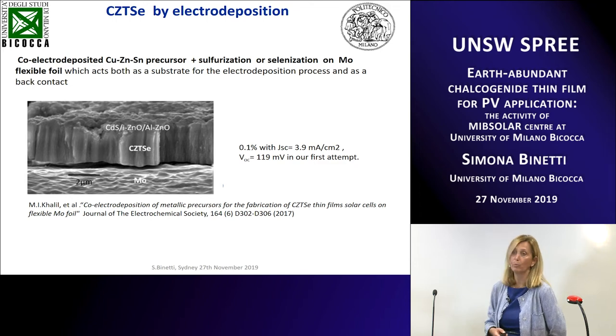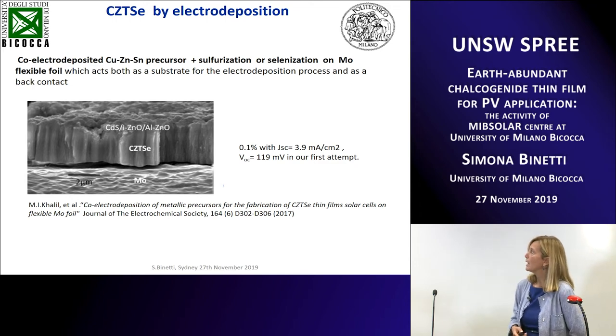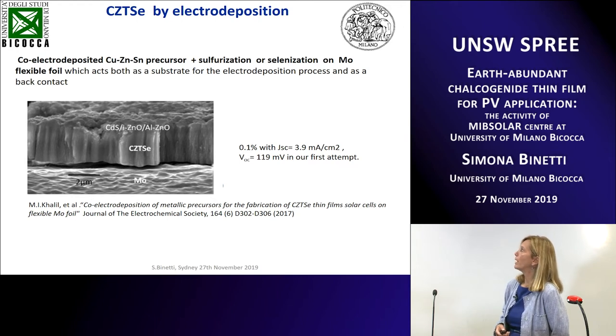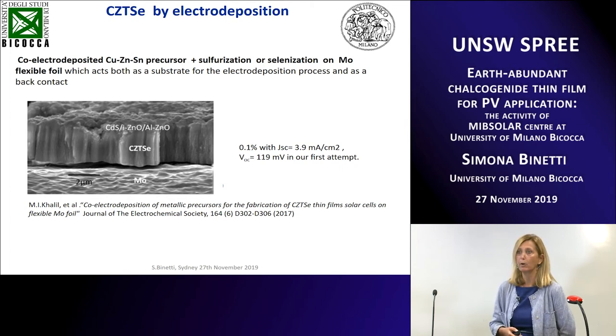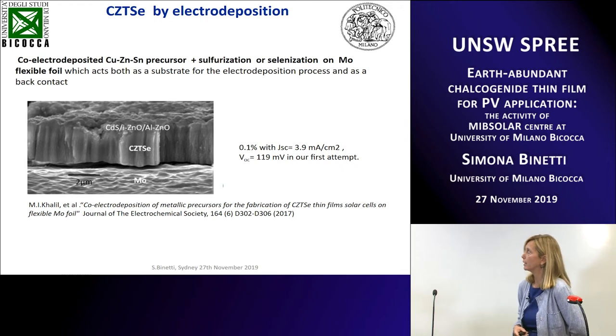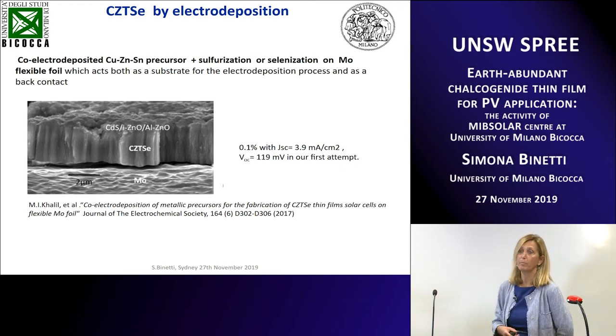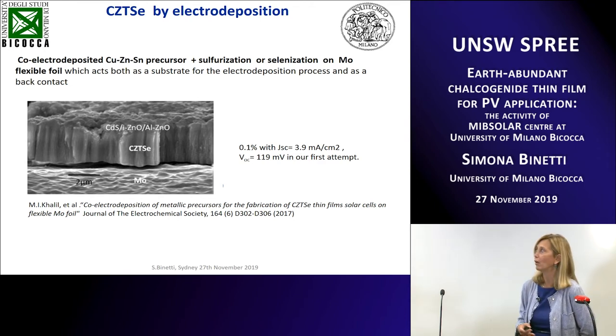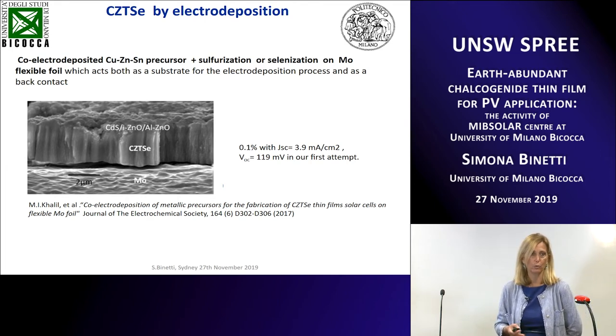We got devices with 0.1% efficiency, but the quality of the film is not so bad. And the advantage of this technique is that, like in this case, you can use the molybdenum as a substrate, but also as a substrate for the electrodeposition process, so as one of the anodes or cathodes, and also as a back contact. So you can directly have a Kesterite thin film on a flexible molybdenum substrate. Of course, the quality of the film is not so high due to the fact that the surface of the molybdenum used for electrochemical deposition is not the best one, but we are working on it.